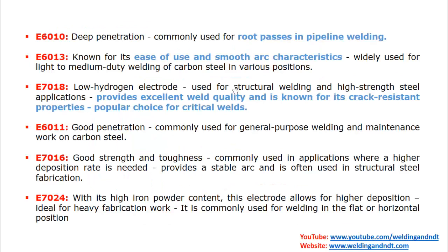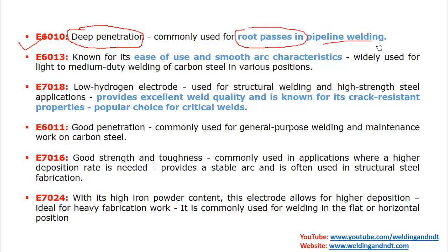Now we will look at the most commonly used SMAW carbon steel electrodes. E6010 is very popular in pipeline welding because of its deep penetration. It is most often used for the root pass in pipeline welding, especially for small diameter pipelines where back gouging from inside is not possible. Good penetration is required, so E6010 is recommended for root pass in pipeline welding.